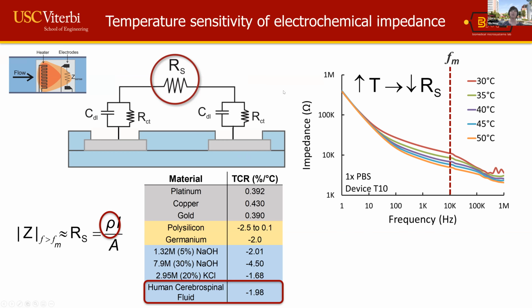It turns out the solution itself, so this material is going to be human cerebrospinal fluid, is quite temperature sensitive, and it's more temperature sensitive than common resistance temperature detector materials like platinum, right? So it's listed down here. And so the idea is that as this heat is carried downstream by the flow, we can actually detect a decrease in the solution resistance by measuring the electrochemical impedance at high frequency, and that then correlates to the increase in temperature.